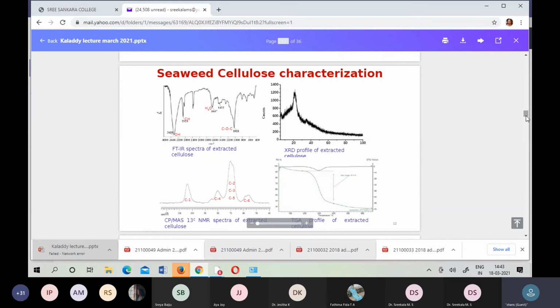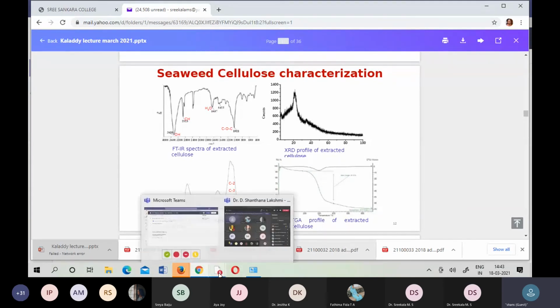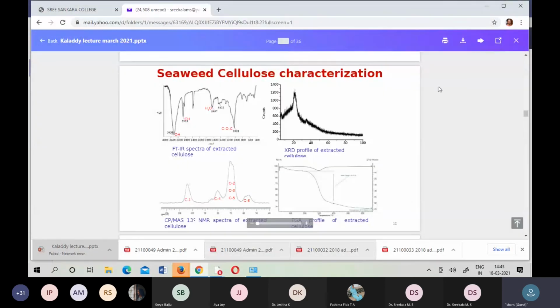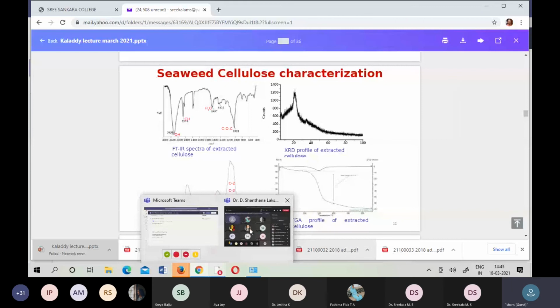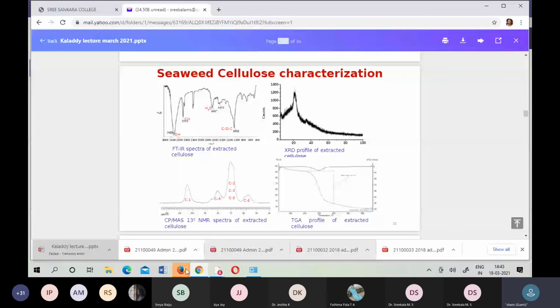This is a quality of cellulose with the matching functional groups, and the XRD peaks show it's not very crystalline, as we expected. And the NMR and the other things, of course, the TGA we did just to make sure, because the seaweed is coming from natural resources, like I mentioned, it has a lot of ash contents. When you see the thermogravimetric analysis, we performed it close to 800 because we are very sure this material has a lot of ash contents.